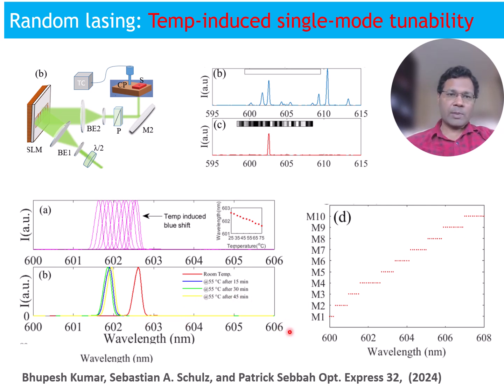Here piecewise spectral tunability over 8 nanometers by tuning 10 different lasing modes has been shown. To achieve this piecewise tunability through mode hopping, the disordered structure must support a sufficient density of modes. Specifically, to achieve continuous tunability over a bandwidth of 8 to 10 nanometers, at least 10 to 15 modes within that bandwidth are required. Here we show piecewise tunability over a bandwidth of 8 nanometers by selecting 8 to 10 different individual modes and tuning them by heating the sample.